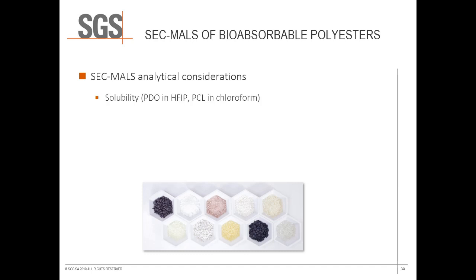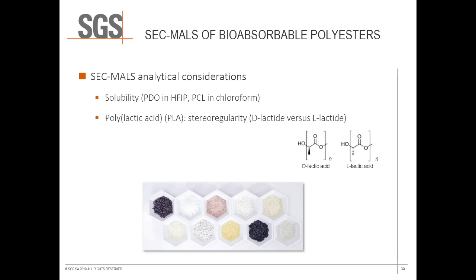Solubility is the first hurdle to overcome. For polylactic acid in particular, this can be challenging if you do not have the necessary information about the sample. Lactic acid exists in D and L configurations. The ratios at which these two are present in a sample containing PLA, and their arrangement in the molecule, have a drastic effect on solubility. Depending on the exact composition, PLA and polylactic coglycolic acid, that is, PLGA, samples may dissolve in tetrahydrofuran, a common SEC solvent that is easy to work with, or may require a stronger solvent such as chloroform or hexafluoroisopropanol.